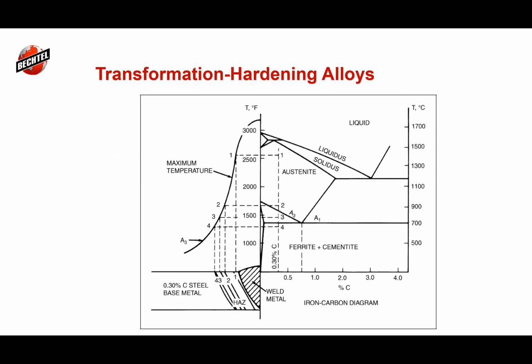So this is a nice picture that talks about this, and this is why I brought the phase diagram up before. On this portion is the phase diagram for iron carbon. And now we have a temperature where we have the base material. This would be similar to an A36, a 0.30 carbon steel base metal, where this ties up to the maximum temperature of the heat affected zone at each distance away.